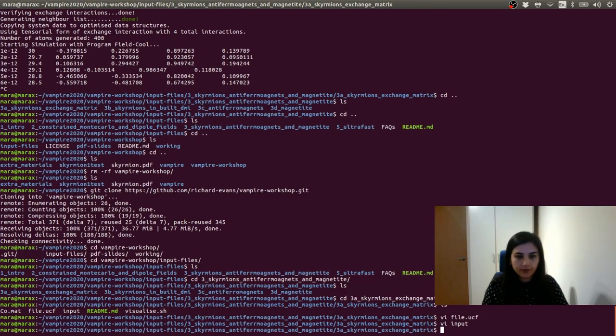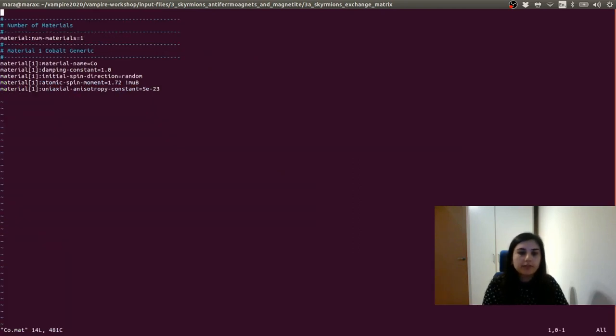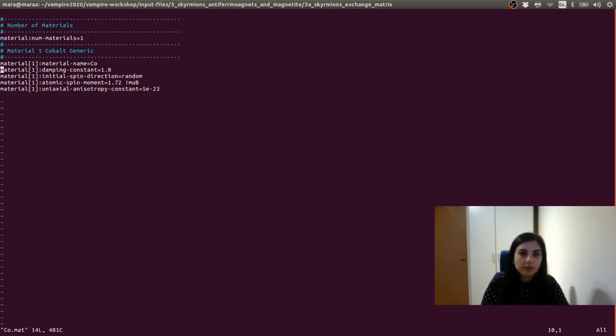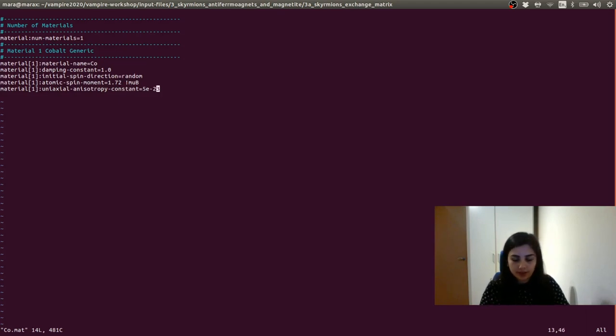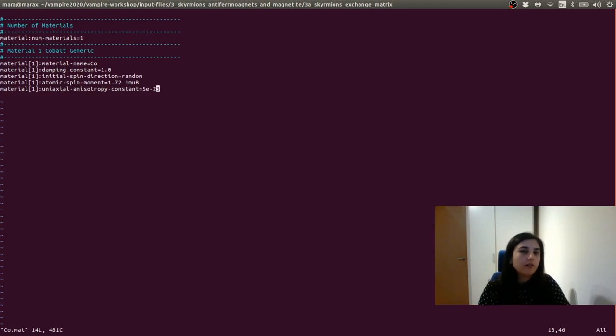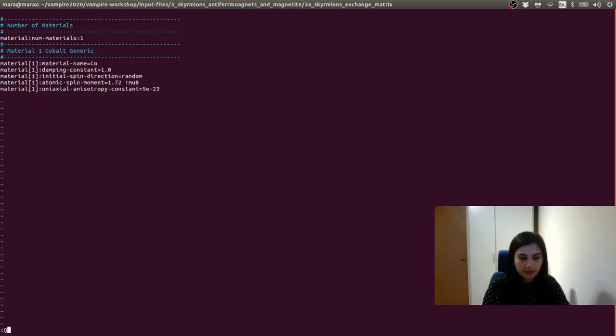Let's also have a look at the material file. The damping constant is set to one — the damping gives you how fast the relaxation happens, and we set it to maximum just to reach equilibration faster. We set up our initial spin direction to random since we are in a paramagnetic state anyway. We have the atomic moment set up to 1.72 Bohr magnetons. We also have some uniaxial anisotropy of this value expressed in joules. This is kind of a toy model just to have an idea of how you can generate skyrmions, but you can parameterize these models much better for more realistic materials.